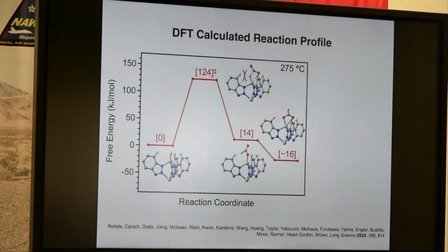So here's the calculated reaction profile. We're going over this large barrier of about 120 kilojoules per mole, and we're forming the formate. And at 300 degrees C, you can go over and back this profile, and you can operate at equilibrium.